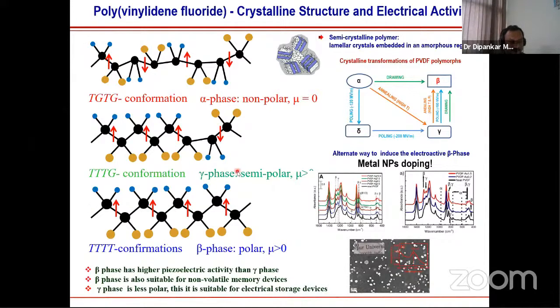In the case of gamma phase, these are the three main phases. In the gamma phase, you can see these three arrows are up dipoles, but one arrow is down here because there is a gauche defect. So this is known as a gauche defect, and these are all trans. So here all are TTT, here T G T G. So TTTG, one is the gauche defect. So this is cancelling it out, so one will still get some polarity. So it is known as semi-polar. So mu is again greater than zero, but it is not fully polar like beta phase. So that's the reason beta phase exhibits a higher piezoelectric activity than the gamma phase.